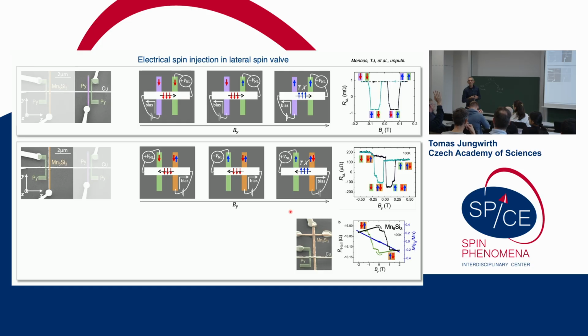Okay. What can I quickly ask? Do you have a microscopic understanding of why applying a magnetic field would actually switch the orientation of the Néel order? Like, do you assume that there's a spin flop or spin canting? Yeah, so this is a general comment for virtually all altermagnets: when you see anomalous Hall effect, that also means that they have, by symmetry, an allowed weak magnetization.